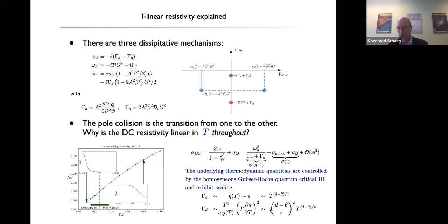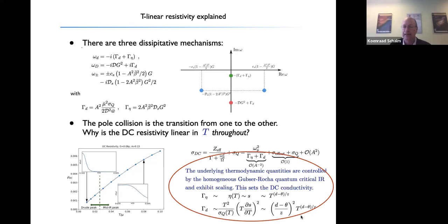look the same, but even in a Reissner-Nordström system, this term is absent. So in a Reissner-Nordström system, you would find that these two objects scale differently, but in Gubser-Rocha, they happen to scale the same way. And it's this underlying quantum critical point that is really what protects the fact that this resistivity stays linear throughout in temperature. Based on the hydrodynamics and the Umklapp hydrodynamics alone, you would again be reinforced in your prejudice that every time you have a transition in the main dissipative mechanism, the resistivity should change in temperature. The beautiful aspect of what happens here is that, precisely because at a deeper level all these thermodynamic quantities are controlled by the Gubser-Rocha fixed point, that is what guarantees that the resistivity stays linear throughout.